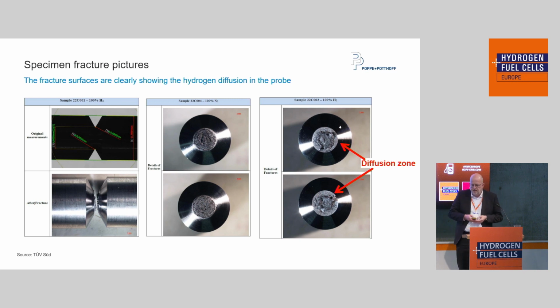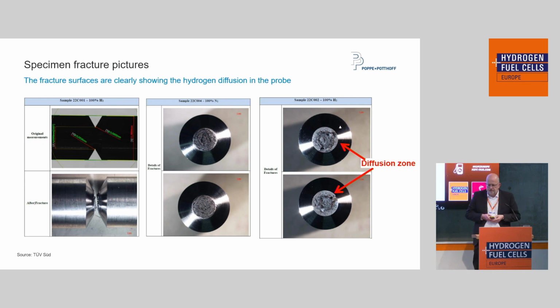If you look at the specimen fracture pictures, in the middle we see the fracture surface of a probe which broke in inert gas atmosphere, and on the right side, one which broke in hydrogen environment. You see very clearly a light gray diffusion zone, but the diffusion zone is not so big that it has an influence of more than 20% on the results.